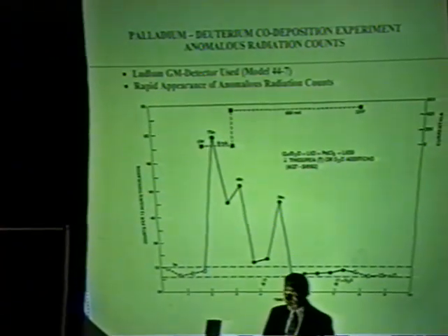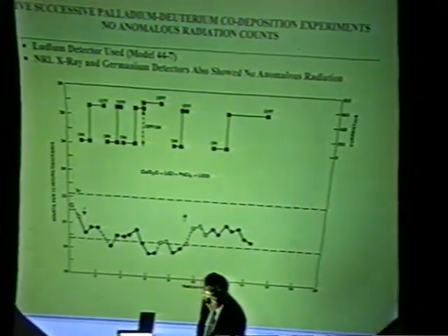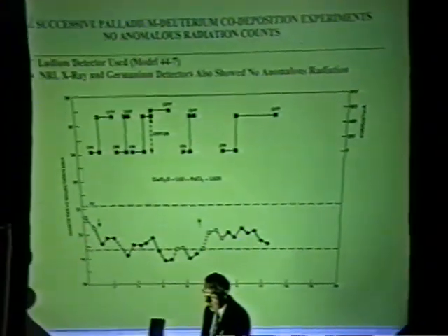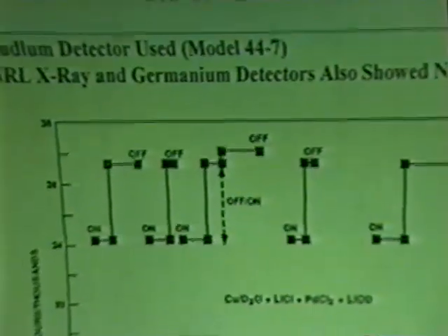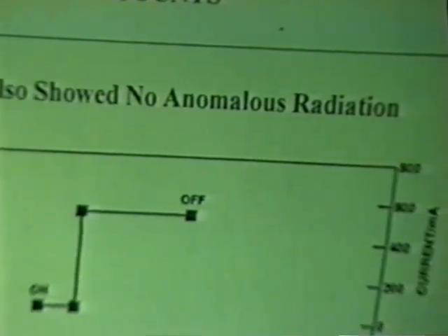There's some problems with it, however. We couldn't reproduce it that well. Another Navy laboratory came with germanium detectors and X-ray detectors to put into our experiments, and we tried to run many experiments quickly while they were there, and we saw no effect. In fact, we had even lower than normal because of the screening by the other detectors that were present, but we could not reproduce the effect while they were there.